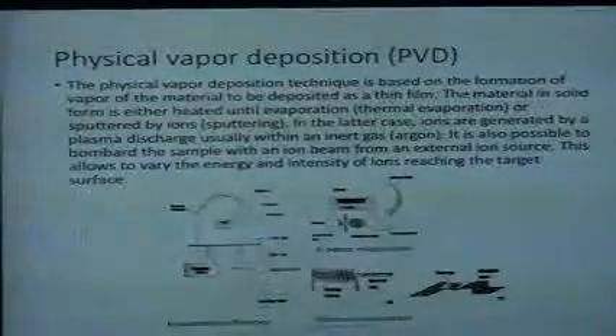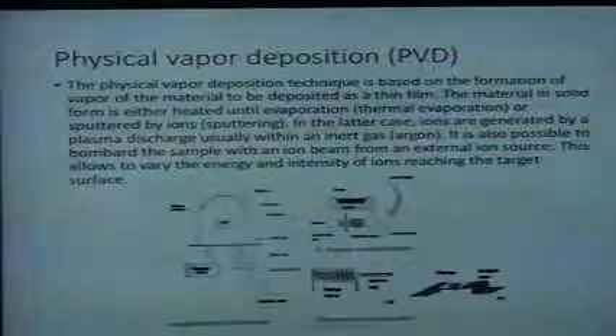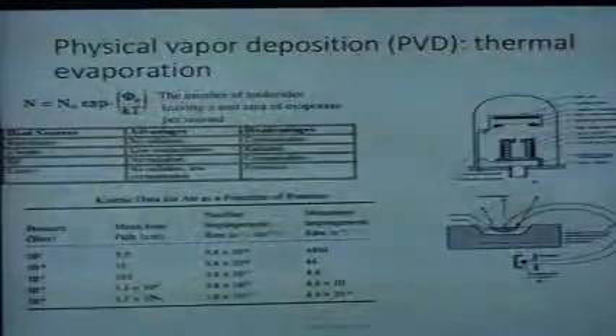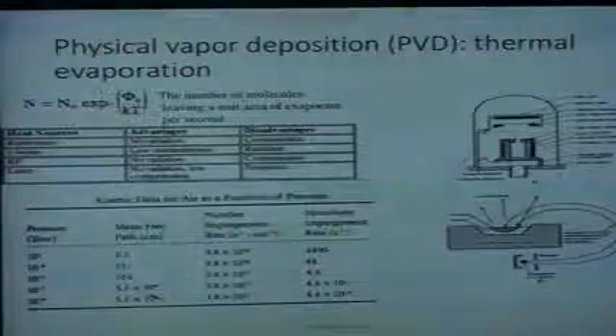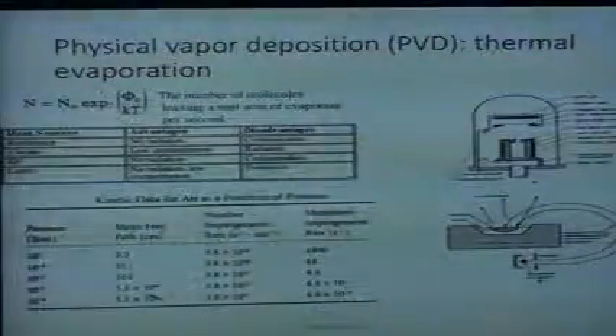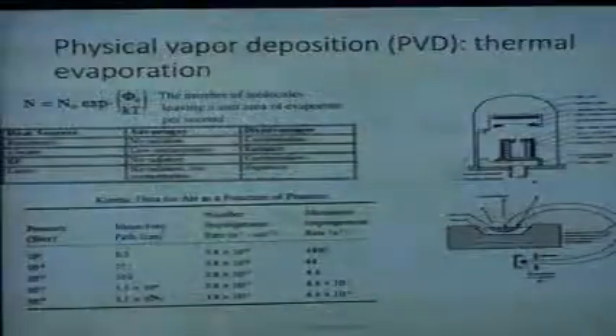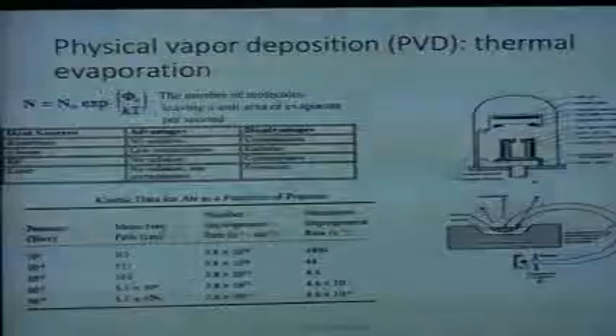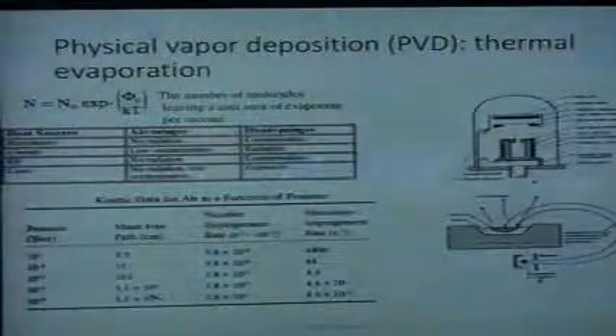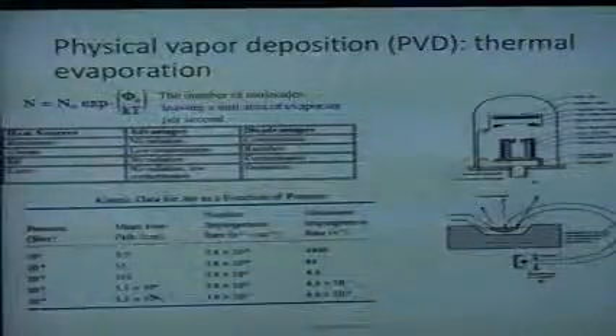In the electron beam evaporation, you're essentially using an electron beam to heat a source and vaporize it. And you can do that with high precision, and you can do it very locally. That's why you use the electron beam. For thermal evaporation, instead of using an electron beam, you essentially use a heater, and you heat up a larger area of that material, and then that evaporates out in vacuum. And there's some principles that you have to follow. When you're looking at thermal evaporation, for example, you can do some quick calculations for how many molecules will leave a surface per unit area, per unit time. And the temperature is important, so if you make it hotter, you'll get more of these things out.